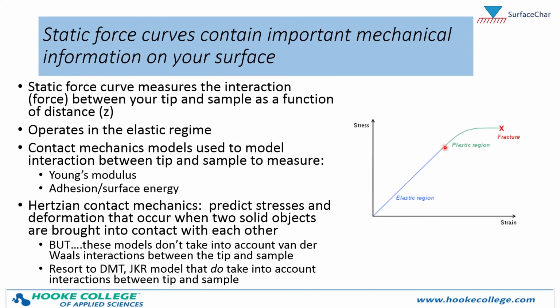As we keep pulling, we get into the plastic region where now there's a nonlinear relationship between the stress and the strain, and then ultimately we fracture the material. But again, our force curves are operating in this elastic regime between our tip and sample. So we collect our static force curves, and then we use contact mechanics models to model the interaction between the tip and sample in order to measure the modulus and the adhesion or surface energy.